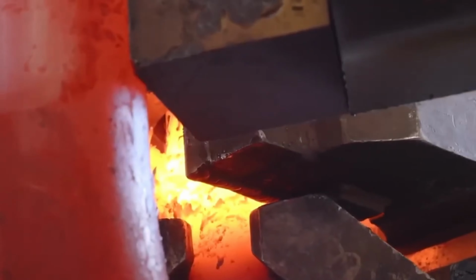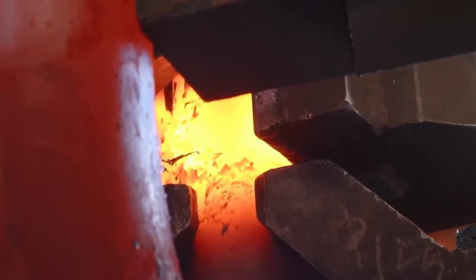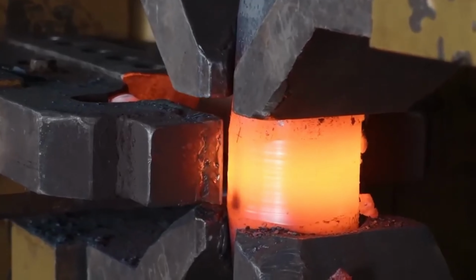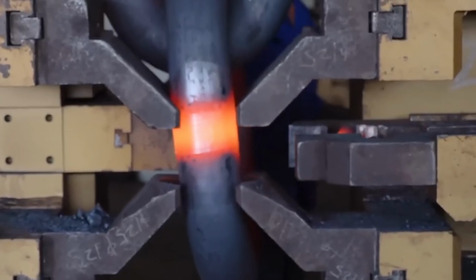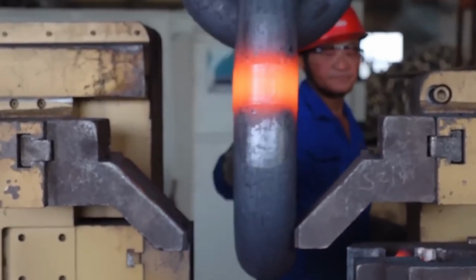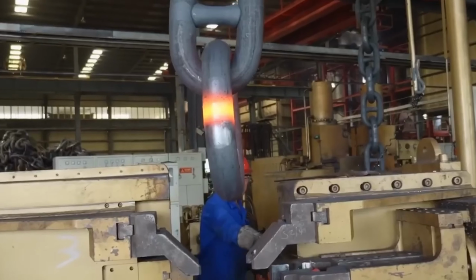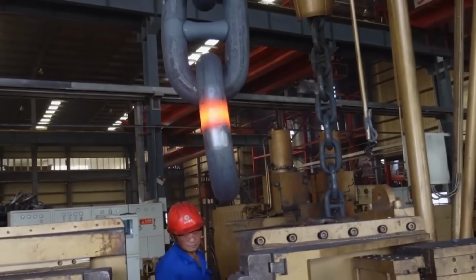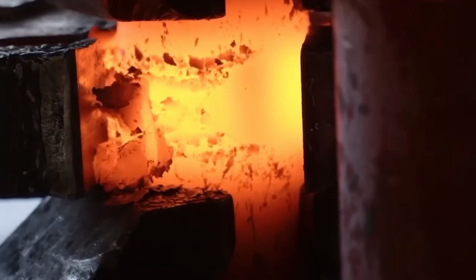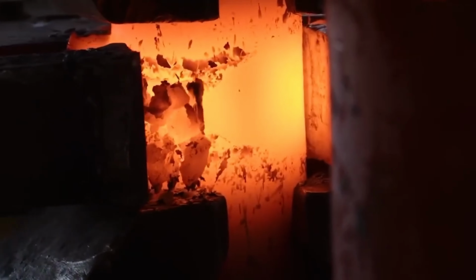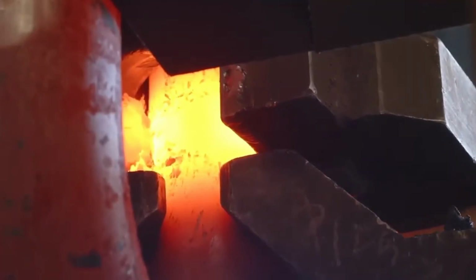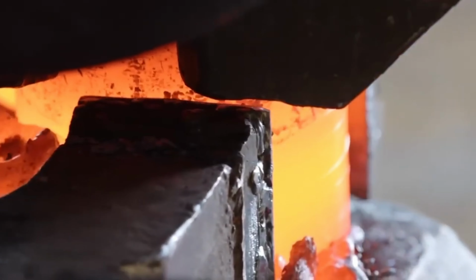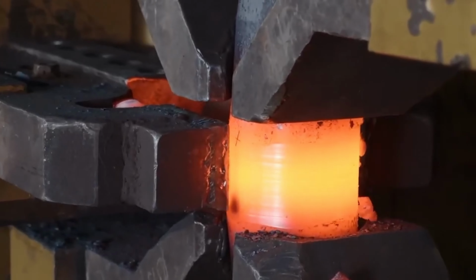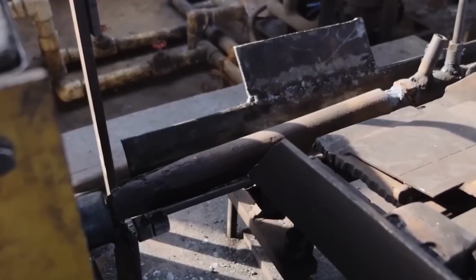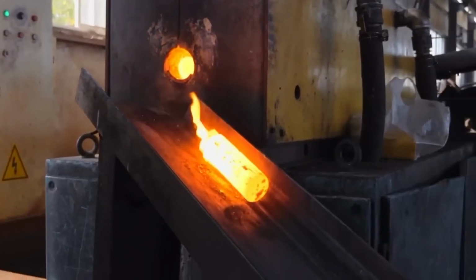The chain passes through a machine that pulls each link into its final shape using controlled stretching forces. This not only ensures uniform dimensions, but also stress tests the weld while the steel is still malleable. If the weld has any imperfection, it will fail here under controlled conditions, rather than in the field. Successful links continue down the line toward heat treatment, one of the most important stages in the entire manufacturing process. Heat treatment determines the chain's final mechanical properties.